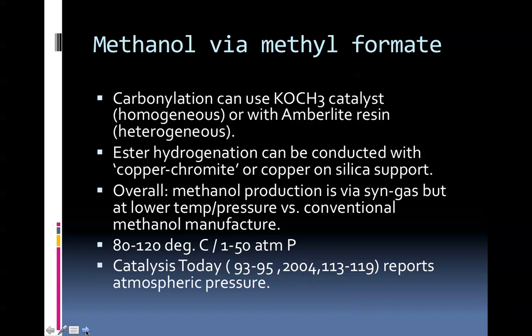Overall, methanol production is via syngas, but at lower temperature and pressure versus conventional methanol manufacture: 80 to 120 degrees Celsius, 1 to 50 atmospheres of pressure. I refer you to Catalysis Today, volume 93 to 95, 2004, pages 113 to 119, which reports atmospheric pressure conditions.